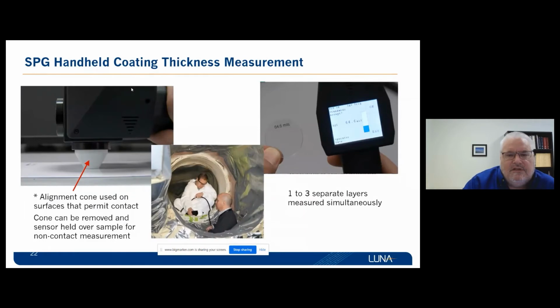So this is just an example of a case where handheld probes may be used. This can be configured either in a contact mode. In this case, where you see this nose cone, the sensor in the upper left-hand corner has a nose cone in contact. That's merely for convenience for the operator. If you were measuring a wet coating, you would remove that nose cone and just move the probe down and it would snapshot the thickness.